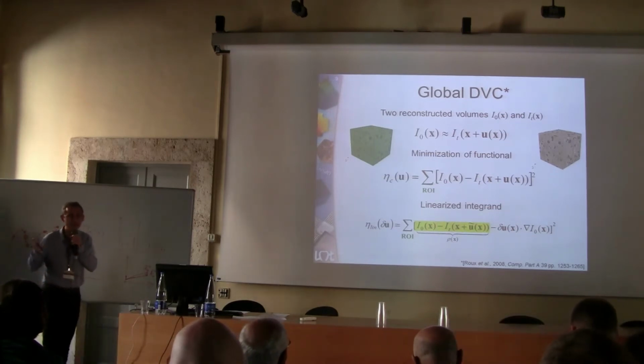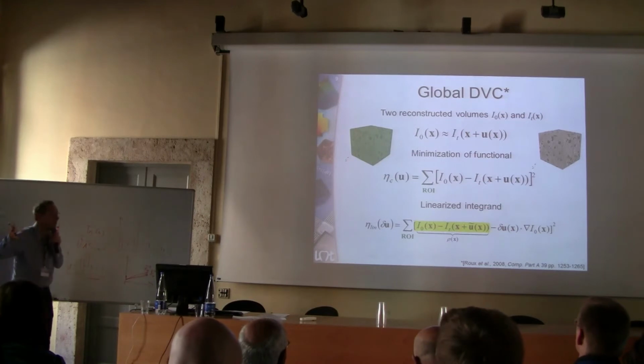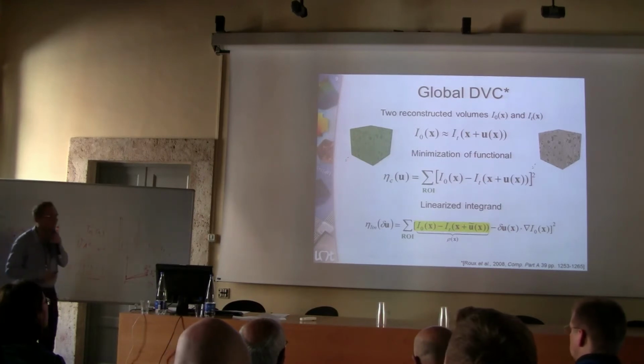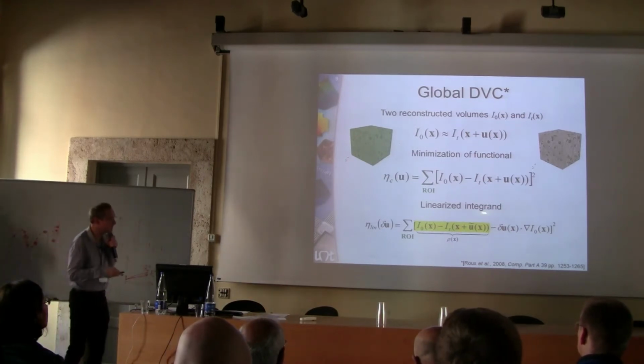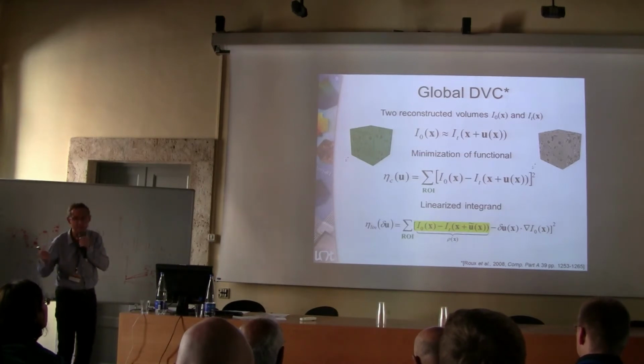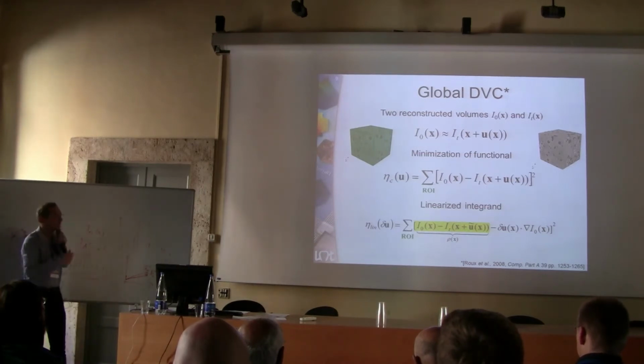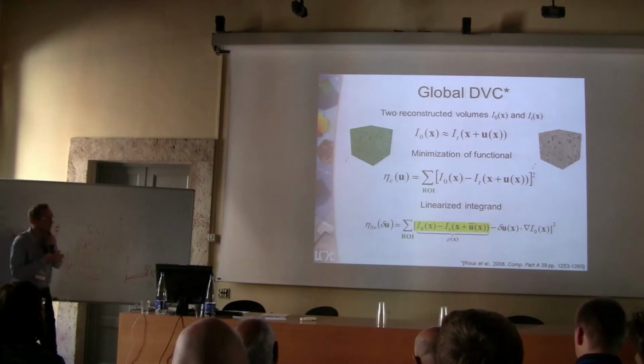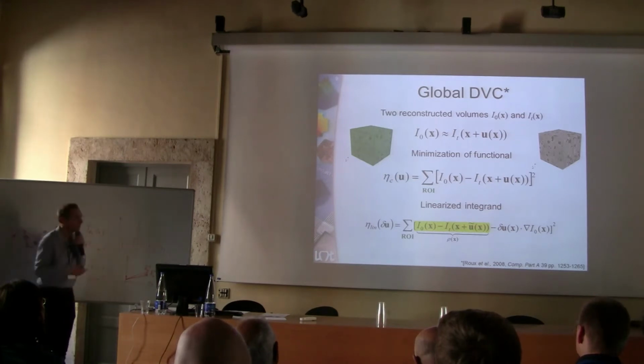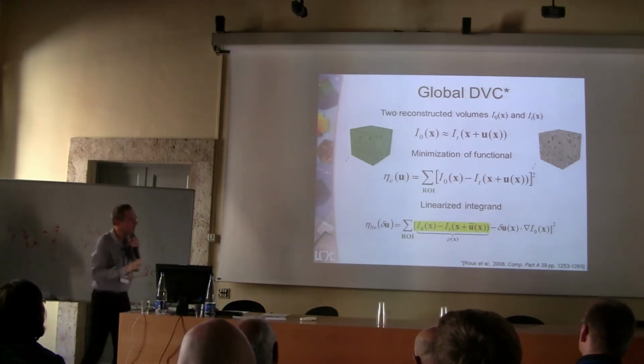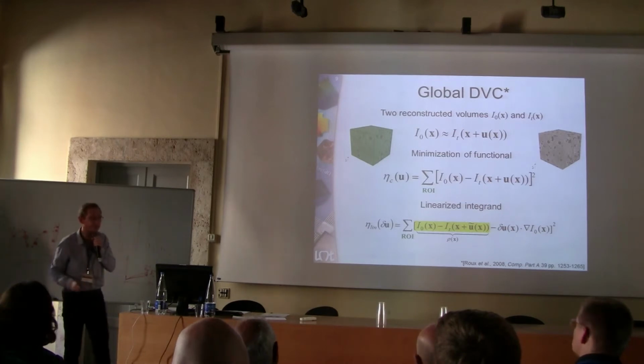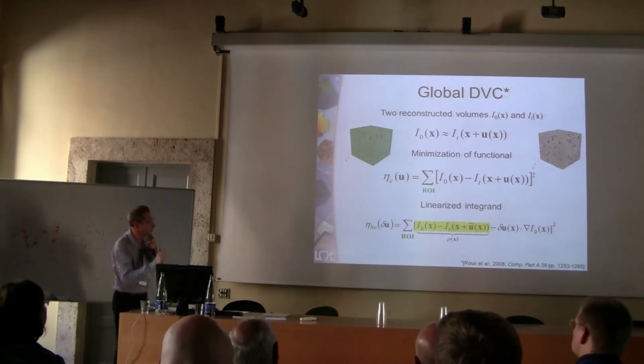If everything works perfectly well, at the very end of the process you should only have acquisition noise, presumably reconstruction artifacts, and things like that. This is very important because you end up with a third volume, and this is the way of controlling that you get a meaningful result, because this type of procedure belongs to the class of ill-posed problems, and you have to make sure everything is correct.